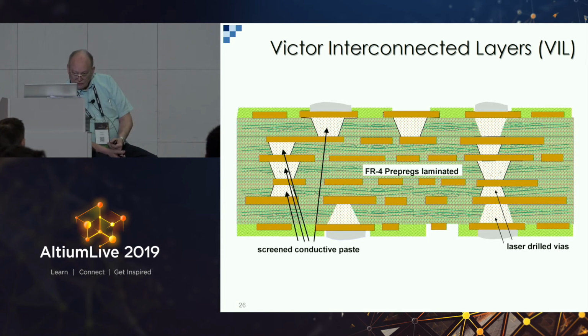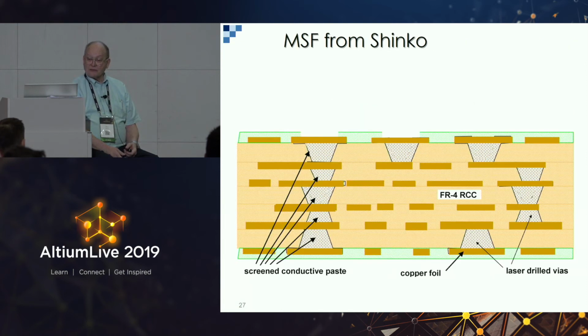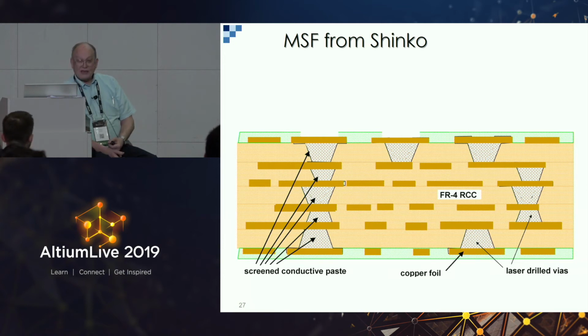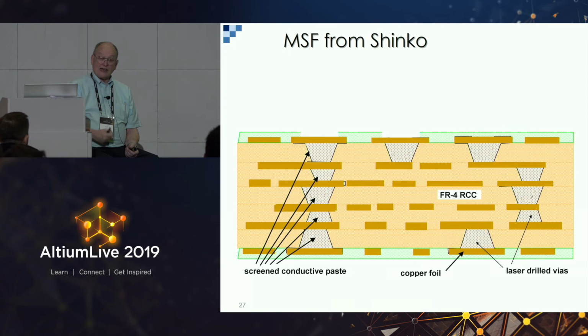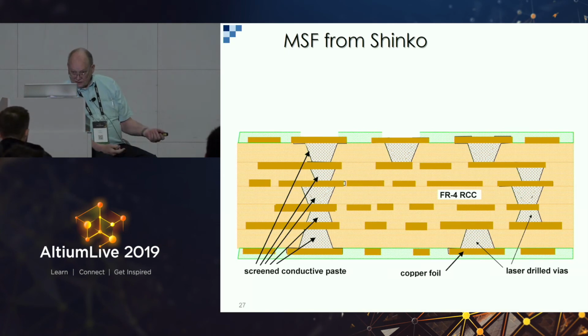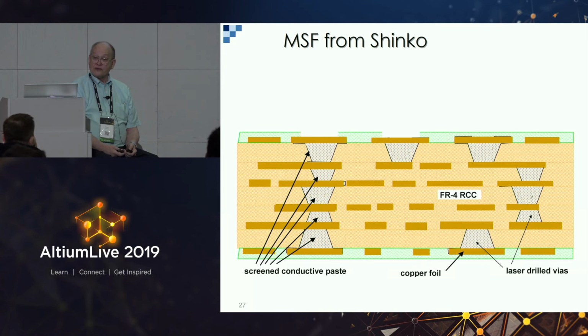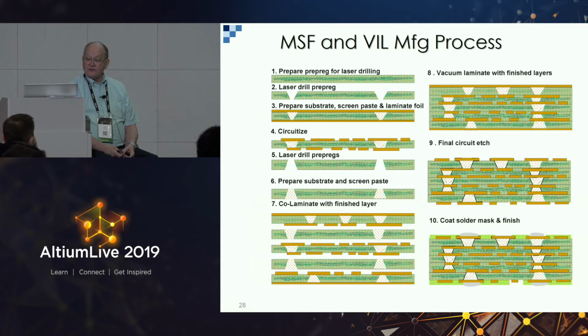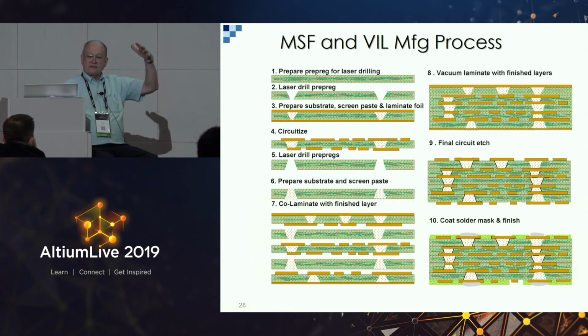And VIL, Victor Interconnected Layers, again, uses laser drilling. It uses FR4 prepreg, and it uses conductive paste, either the silver or the copper type of conductive paste. Same with MSF from Shinko, but they use resin-coated copper, RCC, no glass in theirs, conductive paste, and laser drilling for the vias. And so both MSF and VIL start with the prepreg, laser drill, fill it, put on the copper foil, laminate the prepreg into a core, and then start imaging the outside, and then electrically testing it.